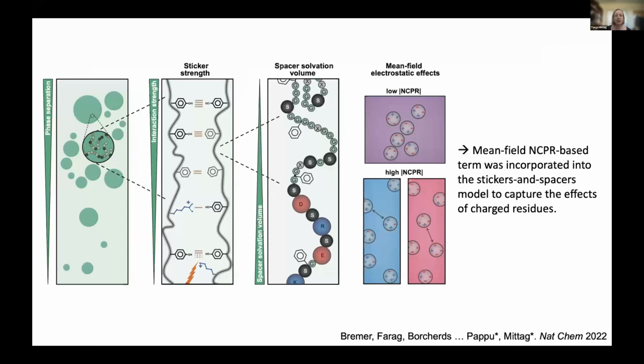And overall, then we come to an understanding of how phase separation is encoded in the sequences of these prion-like low complexity domains. There is a networking component via the stickers, and we can understand which parts of the sequences, which residues are stickers, and their different interaction strength with each other. There's the particular lysine that really interferes with the sticker-sticker interactions. And then there is a density transition, and how well that is allowed depends on the effective solvation volume of the spacers. Charged residues really like to be solvated and take up space, and residues with smaller side chains allow for sticker-sticker interactions very well.